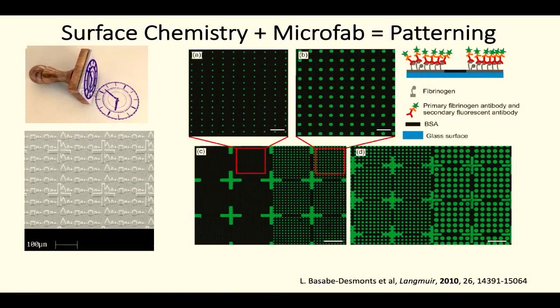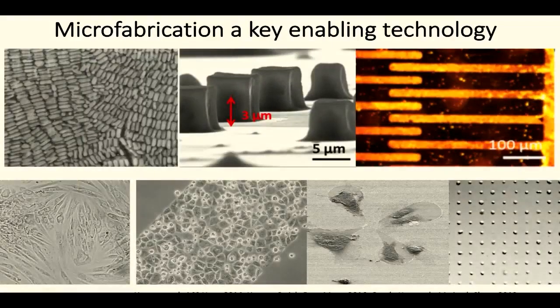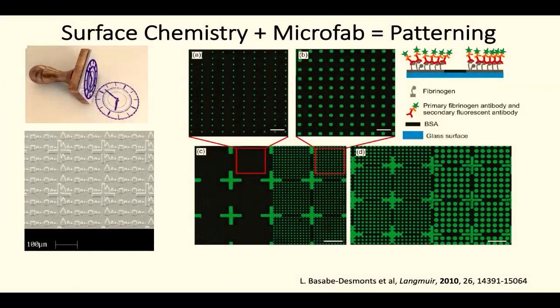So if we have a stamp and we ink the stamp with an ink, in this case blue, I can transfer the blue ink from the stamp to the substrate. That's what we do in the post office. If my stamp contains microstructures, which I can create by photolithography and molding, and my ink is a protein solution, I can create protein patterns on a glass substrate. Proteins adhere very nicely to glass, as many of you know. And as you can see here, we can very nicely replicate any pattern we can create by photolithography.